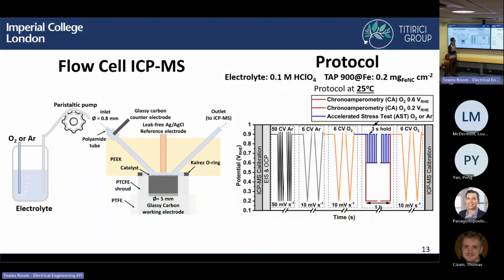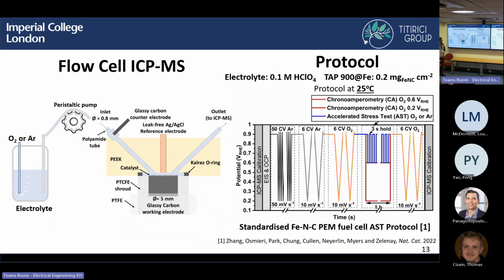So we did all the measurements in 0.1 molar perchloric acid. And we initially conduct 50 cyclic voltammetry cycles in argon to kind of cleanse the surface, as we see in the next slide. And then we do 6 CVs in argon, 6 CVs in oxygen, and then we do a short accelerated stress test for 1 hour, and then we do some CVs afterwards as well. And just to say, the reason why for the accelerated stress test, or AST, we go between 0.9 volts to 0.6 volts, this is trying to follow a recently established protocol for testing these iron nitrogen carbon catalysts in a fuel cell.